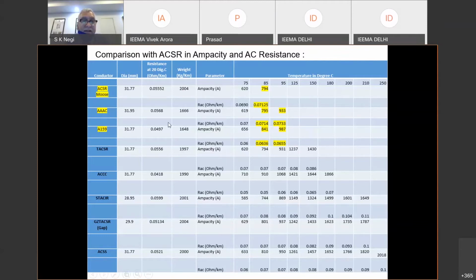So this is a AAAC conductor performance which is better than ACSR Moose. Then here is A159 with the same diameter. We are comparing A159's diameter equivalent to the ACSR Moose, and it is better in terms of current carrying capacity. Actually it is 987 here in this table, but it can go beyond 1030 amps. There are different catalogs from different companies, and here the important point is the resistance, I square R losses. At 95 degrees it has a value of 0.0655 ohm per kilometer, whereas the ACSR Moose conductor is 0.071 ohms per kilometer. Now here the question comes: can you straight away use this A159 conductor compared to ACSR Moose?